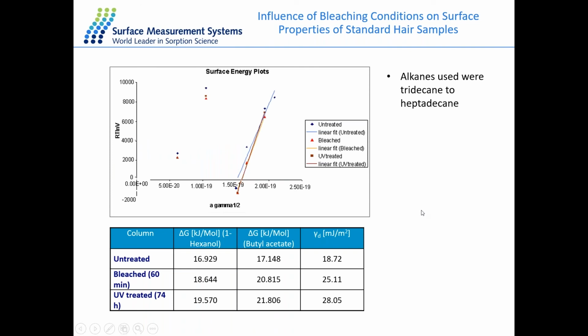So in this case, to calculate the dispersive surface energy, we injected alkanes from tridecane to heptadecane. And we also had a look at some other probe molecules. So we calculated the free energy with a hexanol probe and a butyl acetate probe as well. So these are the results obtained. And as you can see here, by looking at the dispersive surface energy for the untreated hair sample, we have quite a lower dispersive surface energy. So this is indicating a more homogeneous sample.